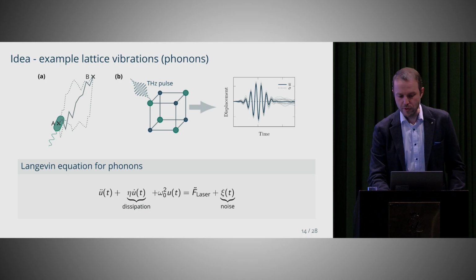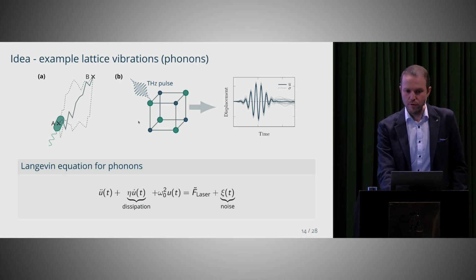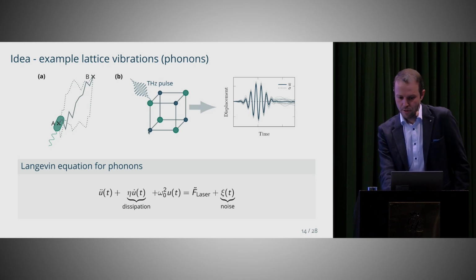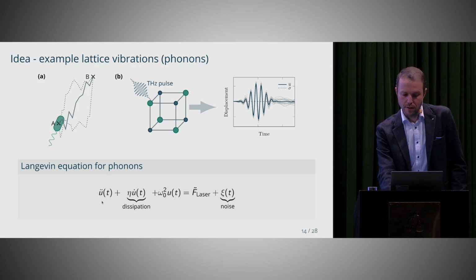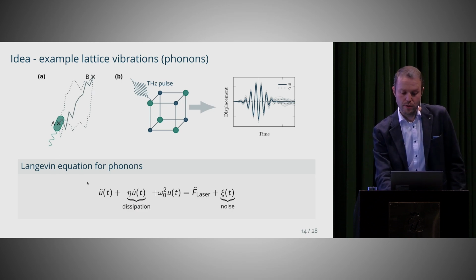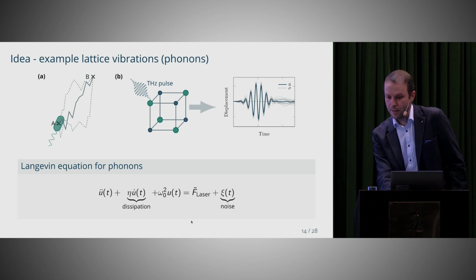So then the claim was, if it works for the bacterium, it should also work for the laser-excited lattice excitation, for instance. There's a classical equation of motion which looks very similar to the bacterium equation of motion. It's a so-called Langevin equation, which discusses stochastic processes. It contains a second derivative of the phonon, that's basically the acceleration of this mode. It contains the dissipation term, its frequency term, a harmonic term, the laser pulse, and the stochastic noise.